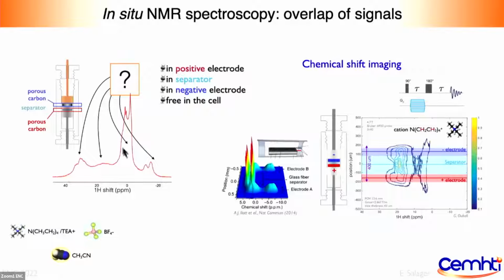So the initial idea was to use this imaging capability, localization capability, to follow the positive and the negative electrode in a regular design. But what happens again here, because you're doing these echoes, by the time you ramp up and you ramp down the gradients, the signal of the strongly adsorbed ions disappears.